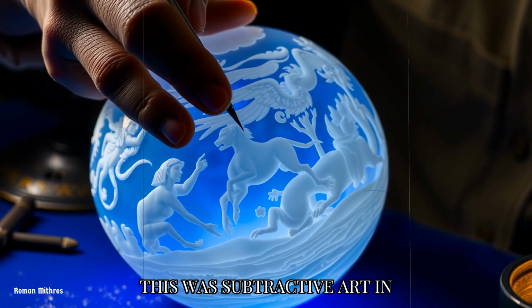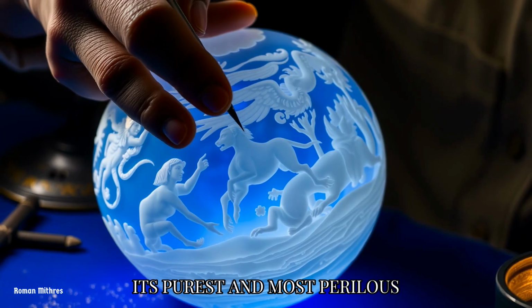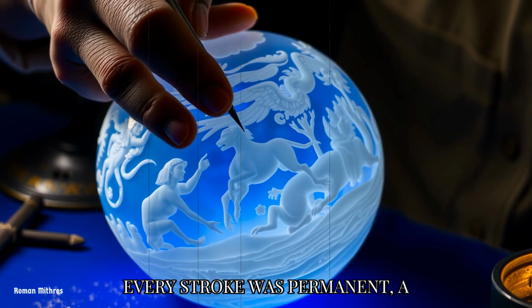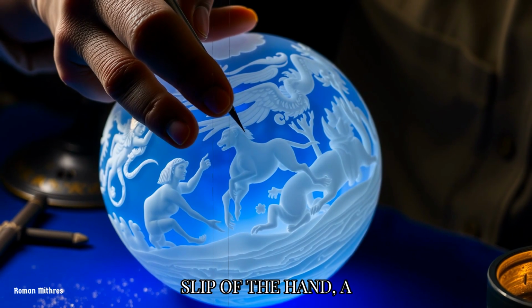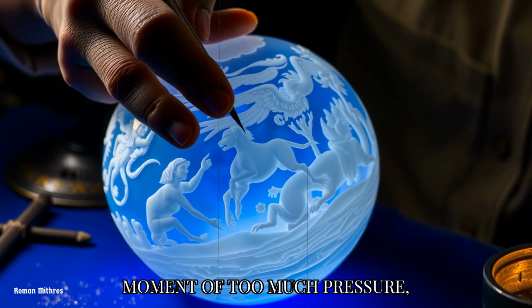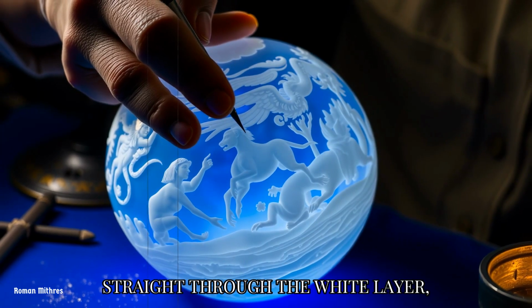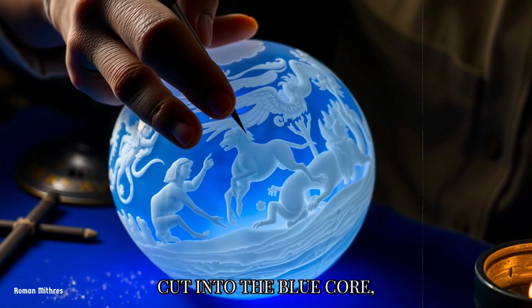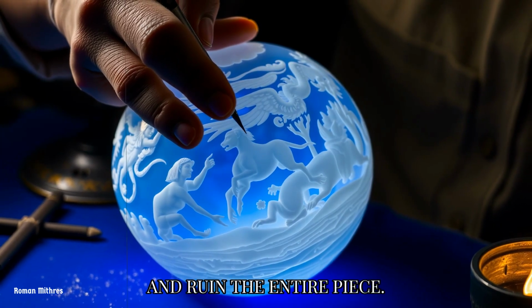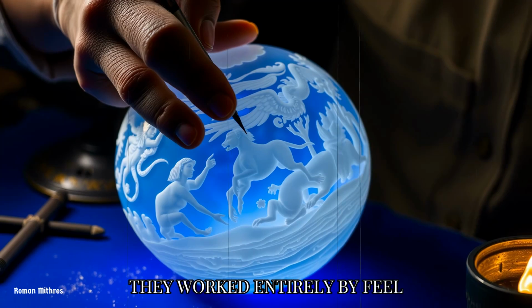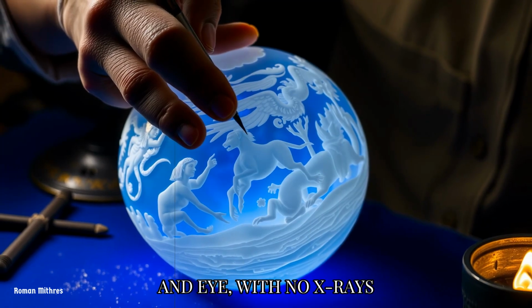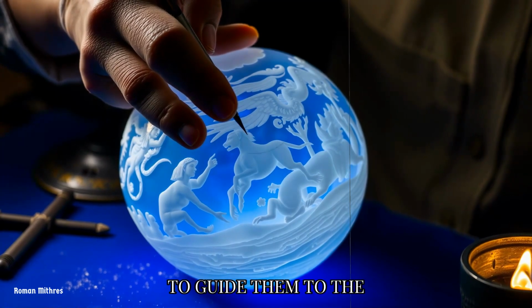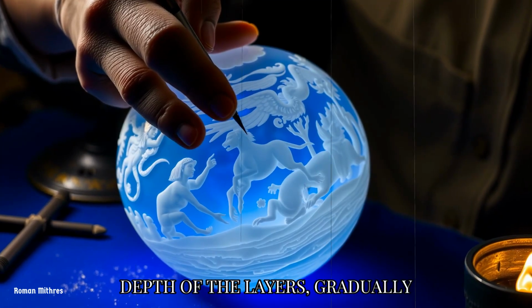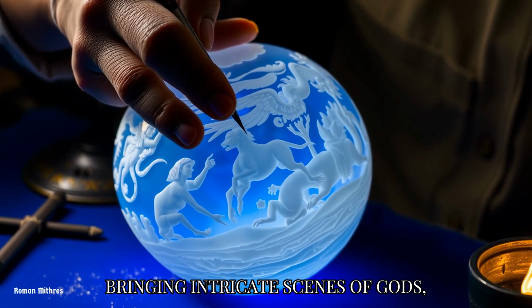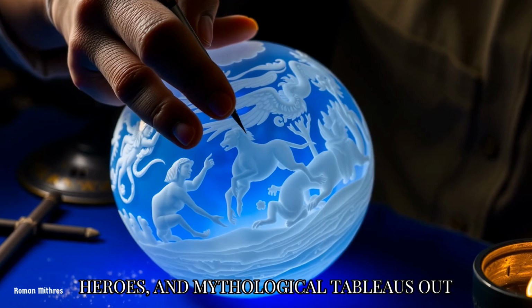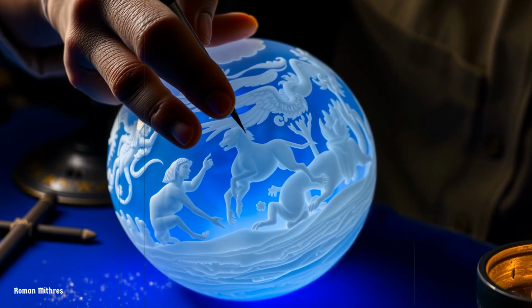This was subtractive art in its purest and most perilous form. Every stroke was permanent. A slip of the hand, a moment of too much pressure, and the carver could grind straight through the white layer, cut into the blue core, and ruin the entire piece. They worked entirely by feel and eye, with no X-rays to guide them to the depth of the layers, gradually bringing intricate scenes of gods, heroes, and mythological tableaus out of the white depths.